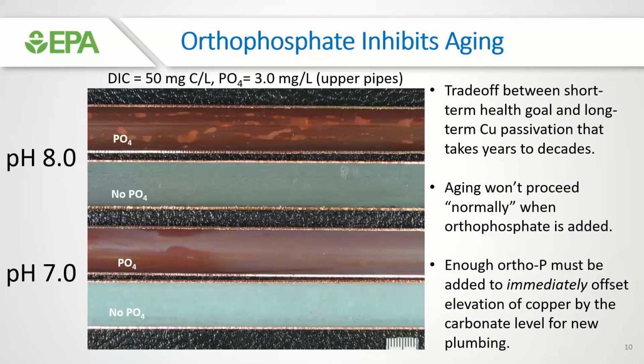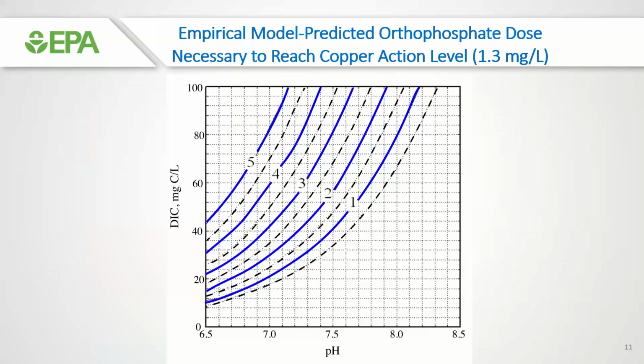Interestingly enough, there's this strange activity that goes on at the surface of the pipe. These are just a couple of cases here from pH 8 and pH 7 experiments that we ran. When you add orthophosphate, it's really strange in that the pipe almost looks new when orthophosphate is present from the beginning, as compared to what happens when no orthophosphate is present. In this case, this looks like a bluish green material, which would likely be the malachite that we do expect to form through aging. So again, the benefits are realized early on, but the aging does not proceed as normal. And again, there's a lot we need to learn. We need to understand what exactly is going on here in the prevention of solids forming on the surface, and what is forming and slowing down the copper levels and copper release.